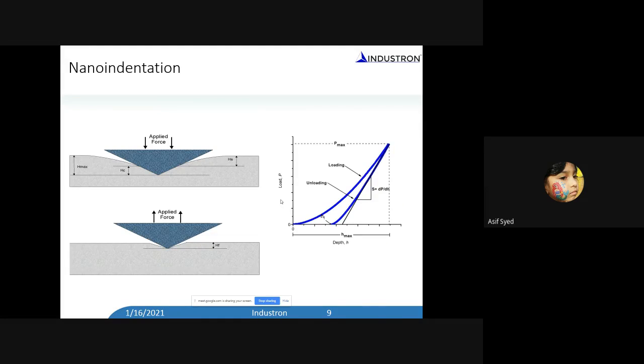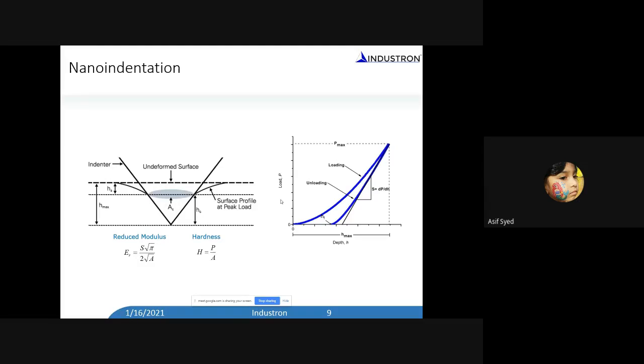Now, with that capability, we can image the surface and have an idea of how it looks, and we can pinpoint a location where we want to do the test, by doing an indentation experiment and creating this load displacement curve. From the load displacement curve, we can measure hardness and modulus. The theory behind this is very simple.